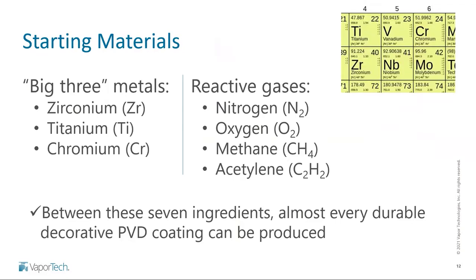It's not exclusive to these. Like I said, any metal can be used, but in order to form the types of coatings that are most commonly used, we use these big 3: zirconium, titanium, and chromium. And by far, zirconium is the most popular, and we'll talk more about that. And then reactive gases. We use very common industrial gases: nitrogen, oxygen, methane, acetylene. These are very common, inexpensive gases, easy to acquire. And between these 7, just these 7 ingredients, almost every single coating we talk about can be made.